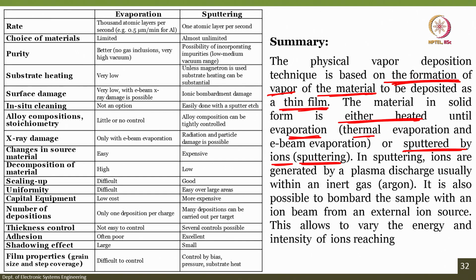Sputtering seems to be like a raindrop on the metal roof, right. If you have ever heard the raindrops falling on a metal roof, that is how sputtering sounds, and that is called sputter. In sputtering, the ions are generated by the plasma discharge, usually with an inert gas, that is argon. And it is also possible to bombard the sample with an ion beam from an external ion source. This allows us to vary the energy and intensity of ions reaching that particular material.